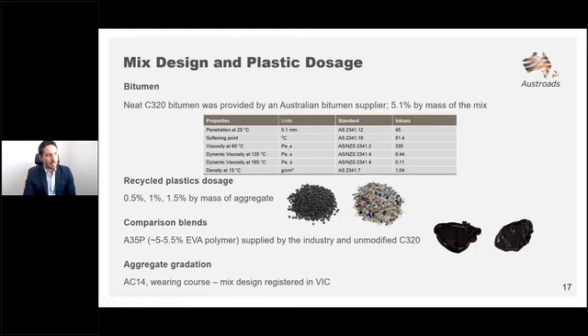The binder content was 5.1% by mass of the mix, and we have used 3 different dosages of recycled plastics at 0.5, 1, and 1.5% by mass of the aggregates. I'm going to show you in the next few slides why a maximum limit of 1.5% was put for this particular